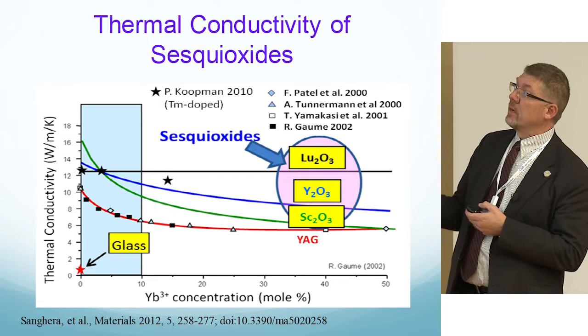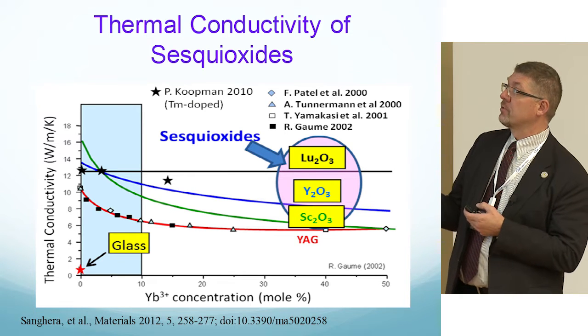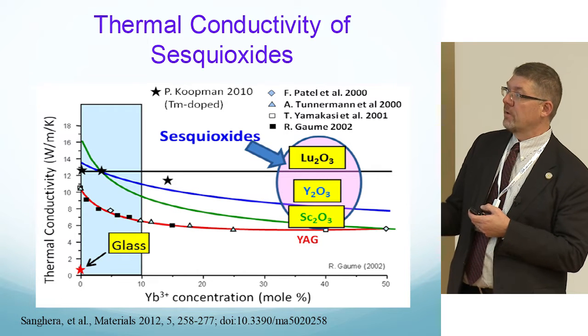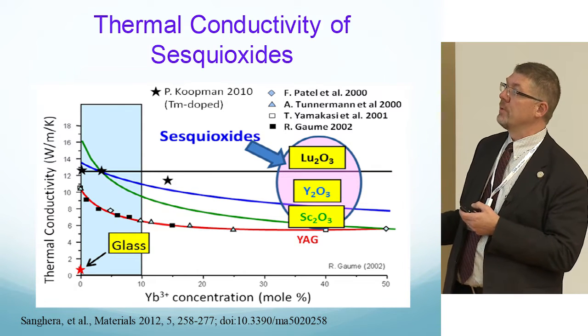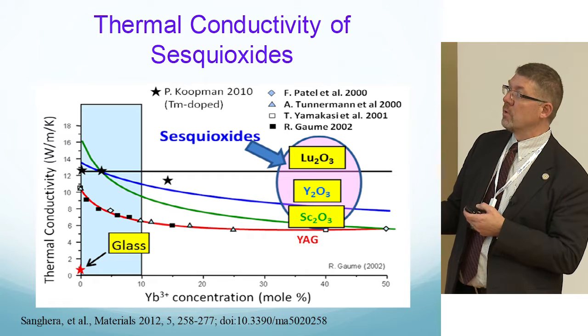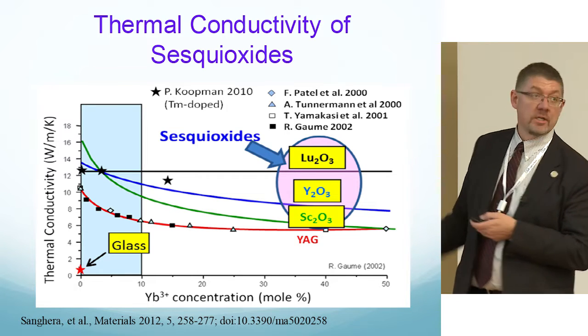Here's the thermal conductivity measured by the various groups that you see up here. Here's lutetia, yttria, scandia. This is as a function of concentration of ytterbium. Here's glass down here. It's horrible. And there's YAG, which sits below all of them.